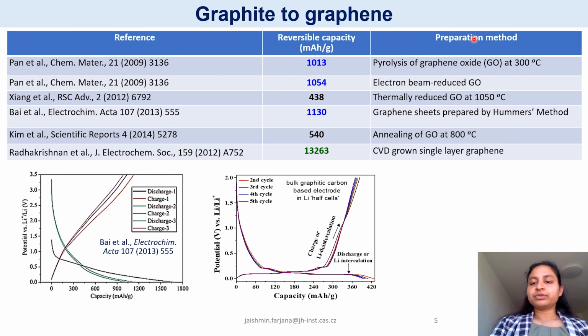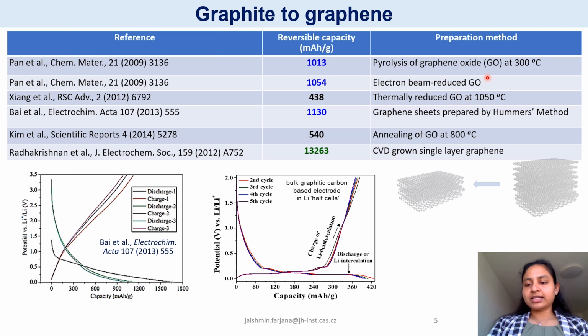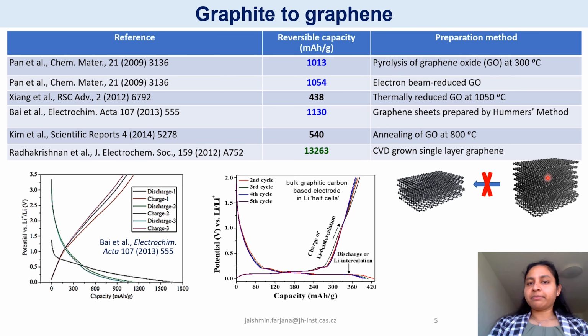And for that, we tried to see that the graphene that is used in the literature for these works is mostly reduced graphene oxide, which mostly has more defects, more oxygen functional groups. So for these cases, it is not only about reducing the dimensional scale from graphite to graphene, but there are multiple other factors that come into the picture. For the graphite, if we have some defects or functional groups on the surfaces, they don't have much role in the lithium storage in the bulk. But when we talk about graphene, then these surface defects or oxygen functional groups have a huge role.